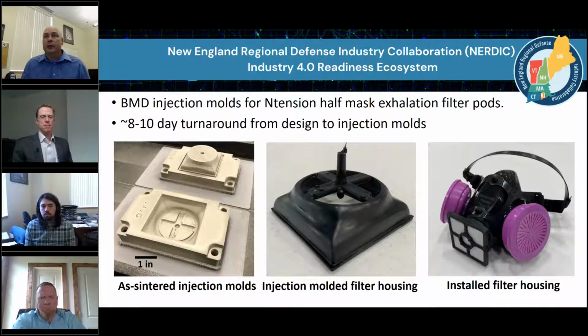And so we worked with them to help design an injection mold. They have a smaller tabletop injection molding machine that's perfect for this application. And we just worked with them to design and metal 3D print these injection molds. We tried doing some initially out of plastic just to get the design right. The plastic ones only lasted about 10 to 15 parts before they broke. With the metal 3D printed molds, they're still running, and they've produced thousands of parts off them at this point.